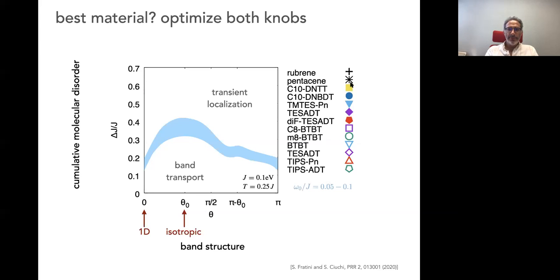And now we can put all these materials on this phase diagram. And so there is some bad luck because they're all on the wrong side. Well, it's good luck for theory because they're on the right side for transient localization theory, but for performances, they're all on the wrong side, and you never hit this band transport regime. And so the funny, or just puzzling, thing is that you have materials that have good band structures but bad disorder, materials with good disorder but bad band structures. And if you could just combine the good disorder and the good band structure, you could probably hit mobilities on the order of 50 centimeters squared per volt second or even higher. So how can you do that?